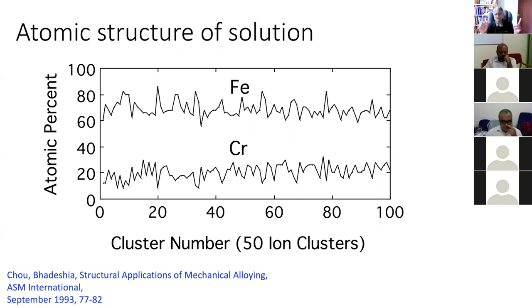Each atom is analyzed using the time-of-flight mass spectrometer and is uniquely identified. So the normal question that I ask when I show this is, can we consider this to be a chemically homogeneous system with a random distribution of iron and chromium atoms? It's very difficult to say, because we obviously have a variation in composition, but is that variation different from if you took 50 ion clusters from a completely random solution?